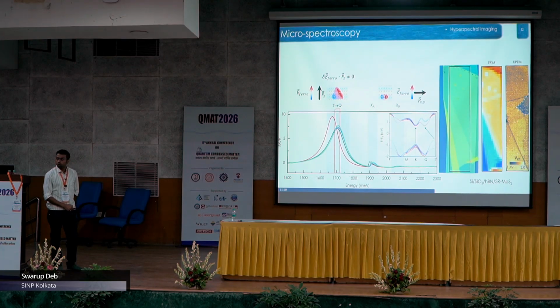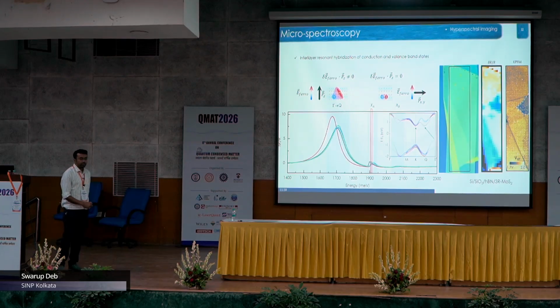So not quite what we anticipated, but later we focused on the A exciton. We also did the same for the B exciton as well, and we immediately see that there is a ferroelectric domain just where we see it in the KPFM. So this was one of the experimental proofs that this ferroelectricity can indeed be probed by spectroscopic measurement. This data was taken at 4 Kelvin, nominal 4 Kelvin, maybe the temperature is somewhat like 8 to 9 Kelvin. But we have experimental data where we can map the same at room temperature from room temperature spectral information.